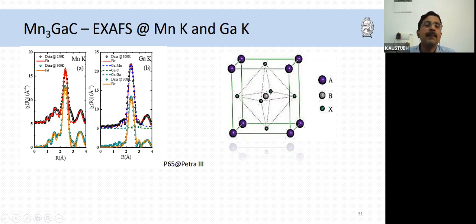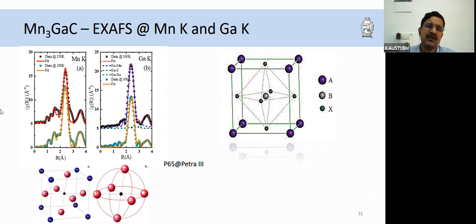But when I look at the manganese edge, at room temperature, I do get a good fit, again up to 4 angstrom. But below room temperature, as I go below, I see this feature which is not accounted for. And this feature actually grows in intensity as I go below room temperature. So we wanted to understand this feature. We tried different things in fitting, and we thought, okay, there should be a distortion of the manganese local structure.